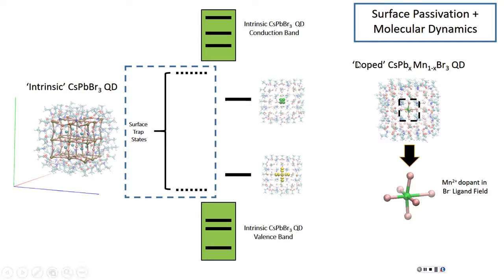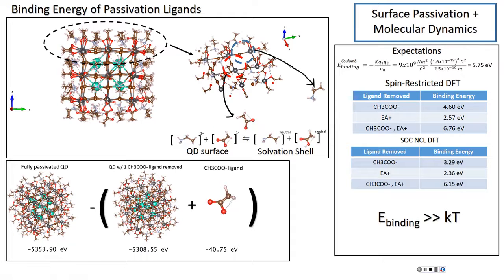And the idea is that in the doped system, even if dual ligands or surface states are created, the dopant doesn't care because it's protected on the inside. So its d orbital states are not going to be interfered with by these trap states. So the first thing to think about is if the ligands are going to pop off, they'd have to have a pretty low binding energy. So a natural thing would be just to look at binding energies of the ligands to the perovskite quantum dot surface. And this top image up here just shows spaces on the quantum dot that I removed ligands from.